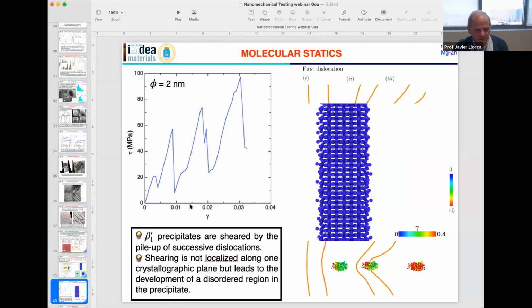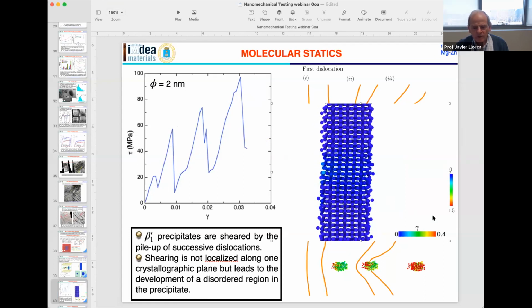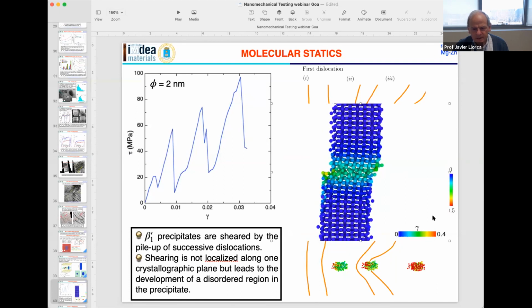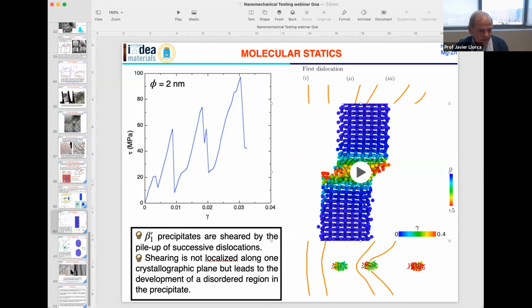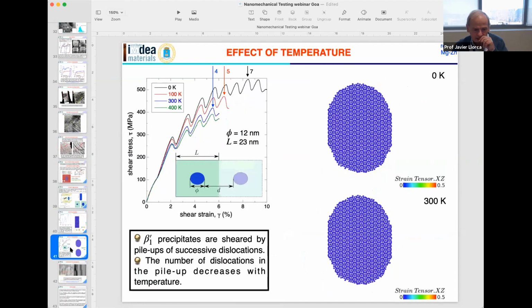This is the shear stress versus the shear strain, and these are the stress strain curves you get. You will see in the movie. So this is the first dislocation that passes and makes a loop, the second, the third, and finally you can see how the dislocation is able to shear the precipitate. And shearing is not localized along one crystallographic plane, but what it creates is a disordered region in the precipitate. So this is interesting because this was very close to the experimental information.